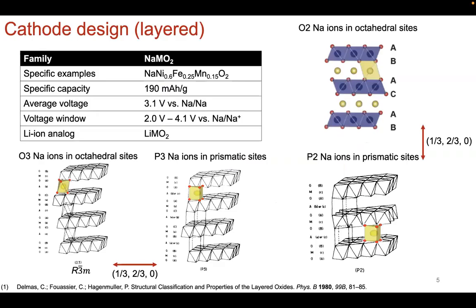So this is where we left off. We left off discussing the layered structure itself. So in comparing with the lithium-ion analogs, we have lithium cobalt oxide. In comparing sodium metal oxide, NaMO2, we talked about how, depending on where the sodium ions sit, that results in different crystal structures. And you can access these structures not just electrochemically. You don't have to just be out of equilibrium. You can actually synthesize these starting materials in the O3, the P3, the O2, the P2.